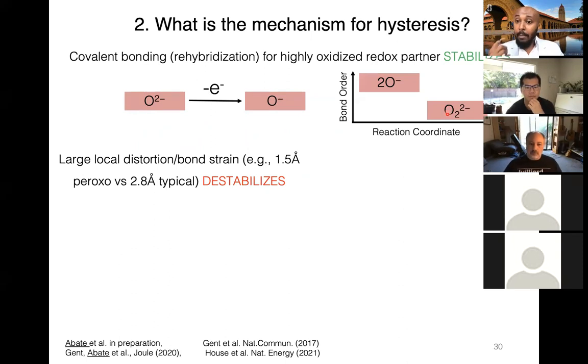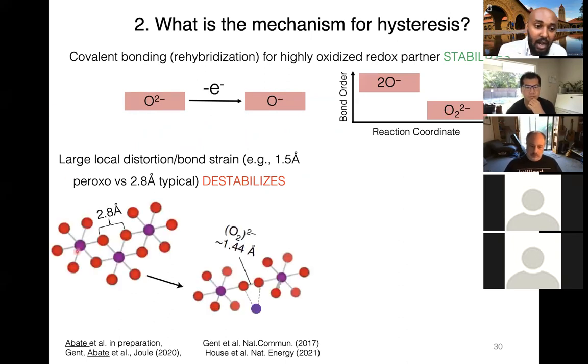local bond strain. What I mean by that is, in the pristine material, as measured from the neutron PDF, the oxygen-oxygen separation distance is close to 3 angstroms. However, upon ionic redox, we are forming an oxygen-oxygen bond that's close to 1.5 angstrom bond length. And this is a significant change in the bond length that's inducing a local distortion and a local bond strain in the material. And the material tries to alleviate this strain by moving the transition metal to a different site, what we call cationic disorder or transition metal migration or hopping.